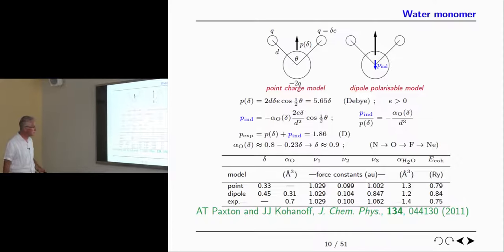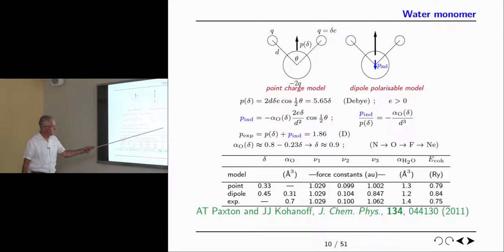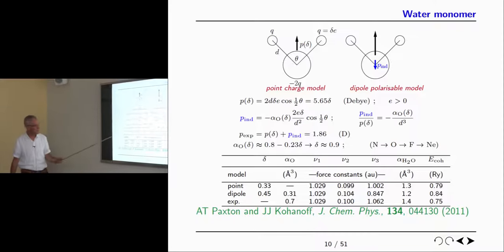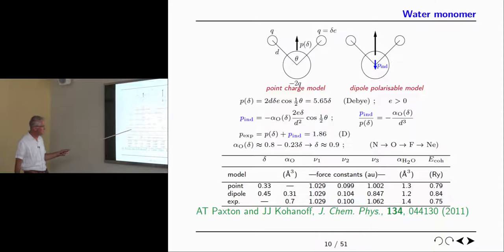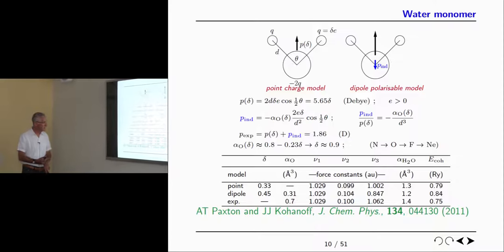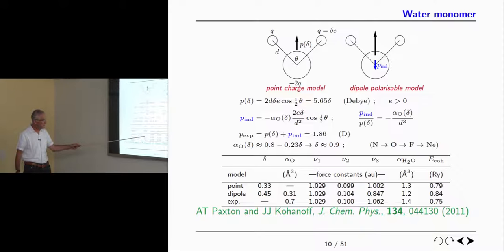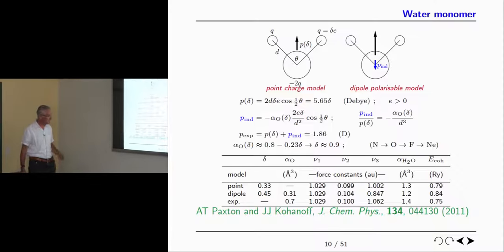I had a clever student who thought about this and said, well, let's look at the polarizability of atoms in the first row as a function of the number of electrons. She just fitted it to a straight line, and so we should be able to predict what the polarizability of the anion is. Unfortunately that doesn't work, so we had to take that as a fitting parameter in two cases. So 0.7 doesn't work, 0.31 is necessary.